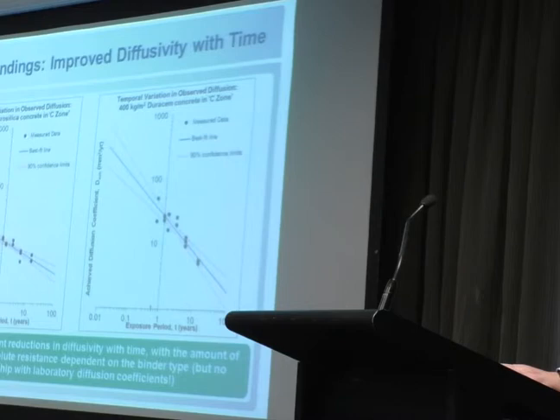And this is an example of the results obtained. So this is the diffusion coefficient plotted against time. Both are in a logarithmic coordinate system to translate the data to straight lines. And you can see that although there is a lot of scatter in the data, there is a statistically significant reduction in diffusion coefficient with time for each of those concretes, and the reduction is much more prominent for the slag concrete on the left than the microsilica concrete on the right, but their initial diffusion coefficients are also somewhat different. So you do need this data to plug into the Fick's law models.